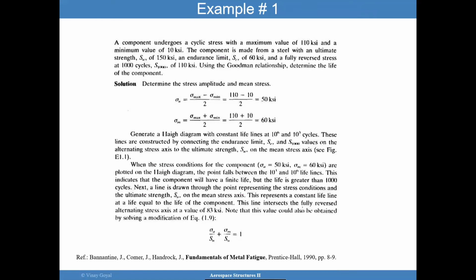It's an interesting example from the Fundamentals of Metal Fatigue book, straight from there. Say you have a component that undergoes a cyclic stress with a maximum value of 110 ksi and a minimum value of 10 ksi. The component is made of steel with an ultimate strength of 150 ksi, an endurance limit of about 60 ksi, and a fully reversed stress at 1,000 cycles of 110 ksi. So they're asking us, using the Goodman relationship, determine the life of the component.